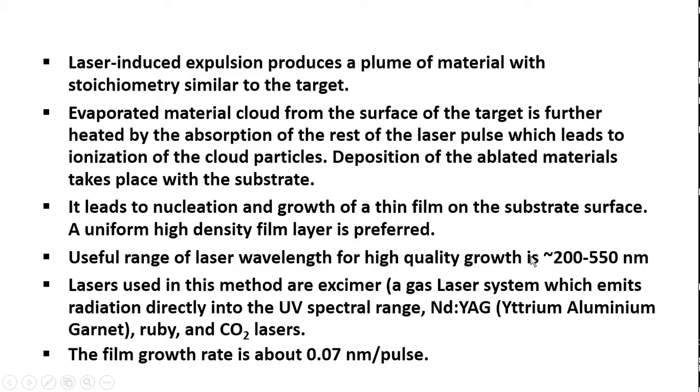Useful range of laser wavelength for high quality growth is 200 to 500, 550 nanometers. That is the wavelength of the laser used. Usually different kinds of lasers can be used in the laser ablation method, in which the laser wavelength can be of the order of 200 to 550 nanometers.